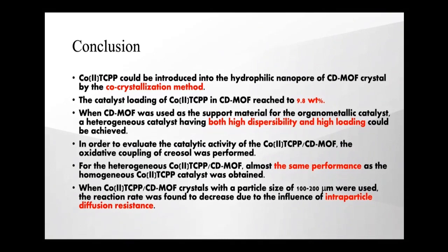In order to evaluate the catalytic activity of the cobalt TCPP CDMOF, the oxidative coupling of creosol was performed. For the heterogeneous cobalt TCPP CDMOF, almost the same performance as the homogeneous cobalt TCPP catalyst was obtained. When cobalt TCPP CDMOF crystals with a particle size of 100 to 200 micrometers were used, the reaction rate was found to decrease due to the influence of intraparticle diffusion resistance. Thank you.